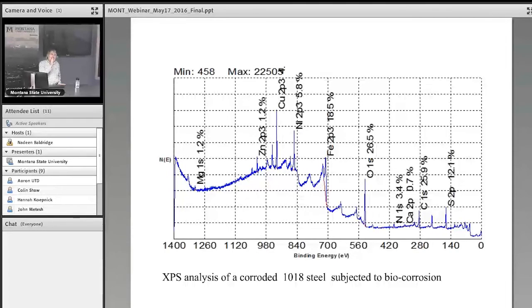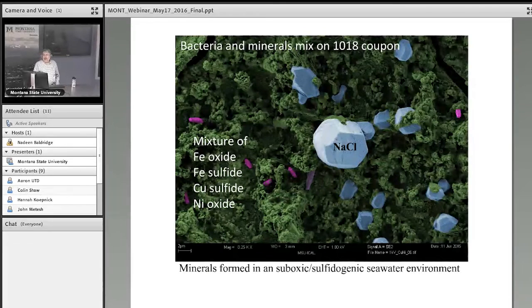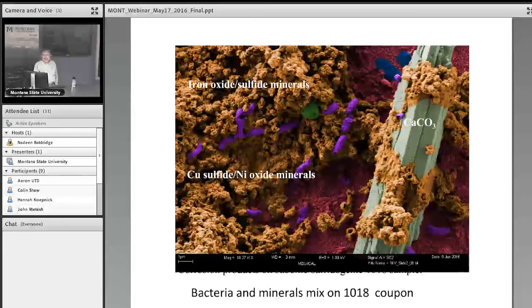So you need this complementary data to be able to tell. Similarly with iron, nickel, copper, the locations of oxidation states are different. That's how you can tell something is oxidized or elemental. We see a lot of elemental deposition on our corrosion product. I never in my life would have believed that I would have pure copper deposited on my surface in a corrosion environment. I always thought they were oxidized. It's not like that. So you can say, hey, this is sodium chloride, this is iron oxide, iron sulfide. You can confidently say so, and then you can also publish your papers, because referees are very smart people.